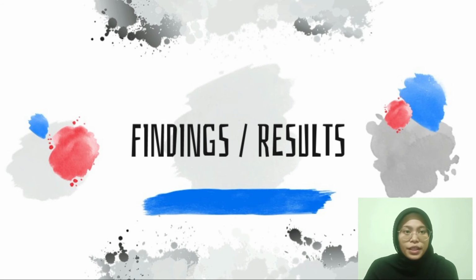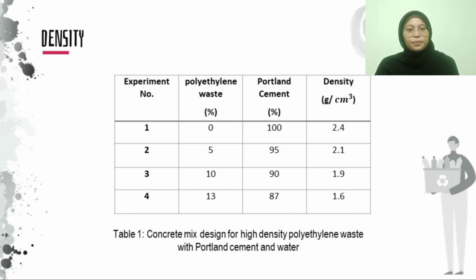For the findings or results, the density of the plastic cement produced in the research was shown in table 1. From the table, it showed that the density decreased as the percentage of plastic waste increased. The difference between them was from 2.4 to 1.6 of the density.